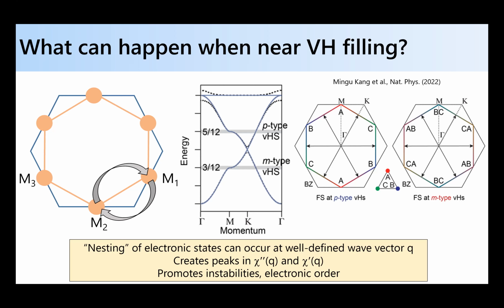And for kagome metals, there are two separate flavors of Van Hove singularities: a so-called M-type, or mixed-type, Van Hove singularity. What that means is that the states at this point are derived from multiple sublattices in the kagome network. There are 3 sublattices in the kagome network, so these are coming from 2. And then there's a so-called P-type, a pure-type Van Hove singularity, where the wave functions are derived from just a single sublattice in the kagome network.